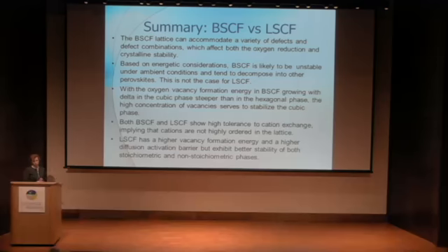With an oxygen vacancy formation energy in BSCF growing with delta in the cubic phase steeper than in the hexagonal phase, high concentration of vacancies actually serves to stabilize the cubic phase. So without vacancies, BSCF is much less stable under ambient conditions than the hexagonal phase. And this kind of contradicts the experiments, right? So the explanation is that when the material has high concentration of vacancies, the cubic phase is stabilized.